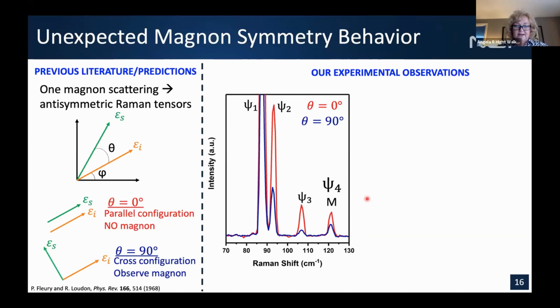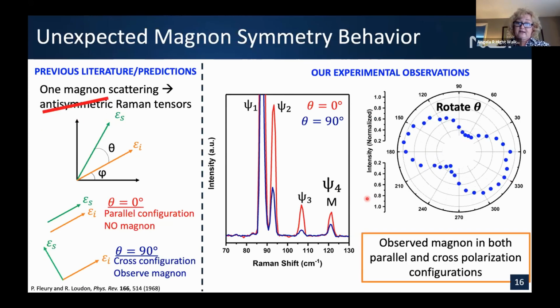So we were a little nervous about claiming vigorously it was a magnon just because of that slight thing. But we were able to do, again, the full polar plot, and it is clear that this is a magnon, again, due to the temperature response and the magnetic field response. And what we think is happening is that in this 2D limit, if you will, this particular rigorous definition of what's permitted and not is really not valuable. In fact, the paper as written is not incorrect. It was the way that people had been using it.